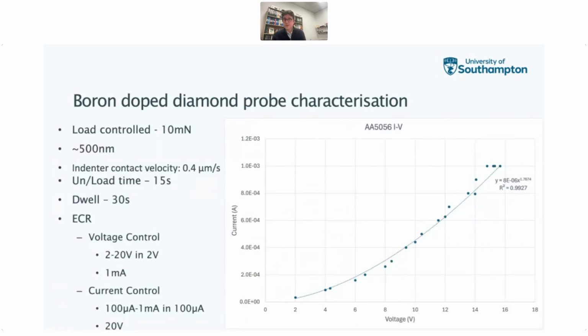We can then start characterizing the probe a little bit. So we'll push it in to about 500 nanometers, 10 millinewtons, and we'll load up and hold it there for a few seconds while we take our reading at depth and withdraw. And we can do this two ways. We can do this in what's known as voltage control or current control. So in voltage control, we can set an upper limit to the current and then specify the voltage. And we've done that in 2-volt increments in this particular case. Or we can do it in current control, where we set an upper limit of 20 volts, for example, and then control the current, specify the current, and let the voltage float up to that maximum value.